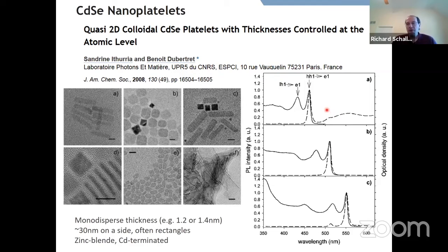So these materials are remarkable in that they have very strong narrow transitions, that are ultimately narrower than 0D nanoparticles of the same composition. And that's because their thickness is very precisely controlled. The material planes, the large flat lattices, like to be exactly one thickness and not a series of different thicknesses for the same particle. And you can make ensembles of these where you just have that one thickness of platelet. And as you step up in thickness, you can get to these different band gaps. You can step this up still redder than what I'm showing you here too.